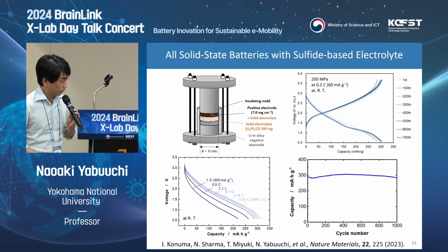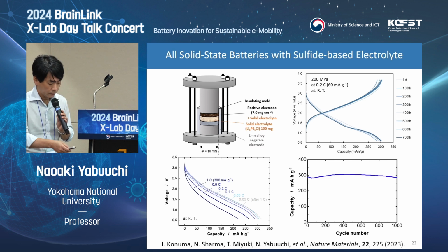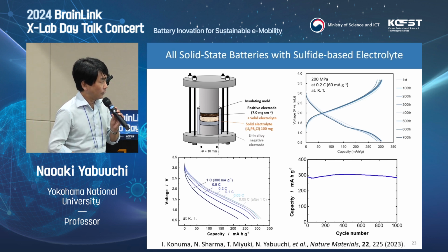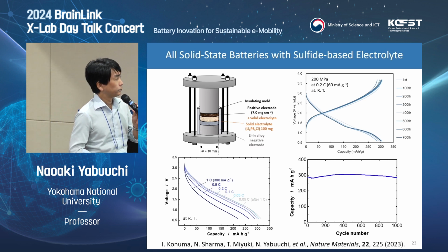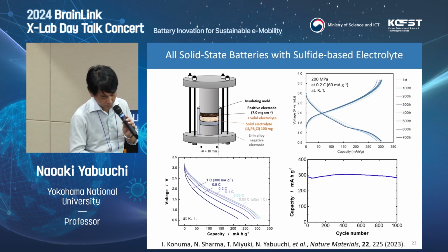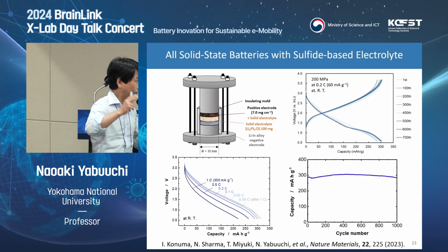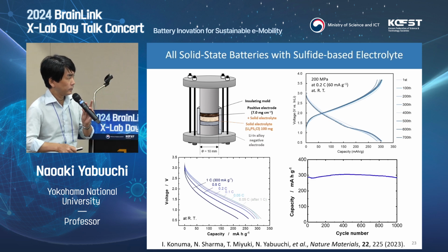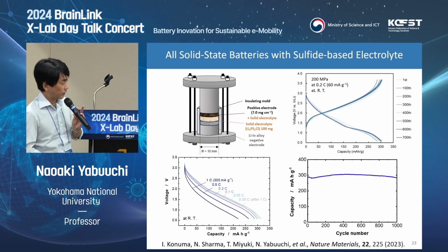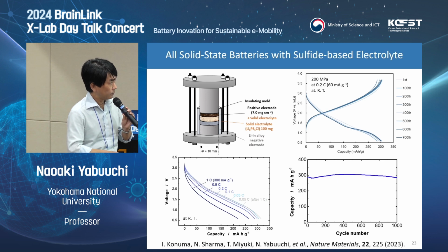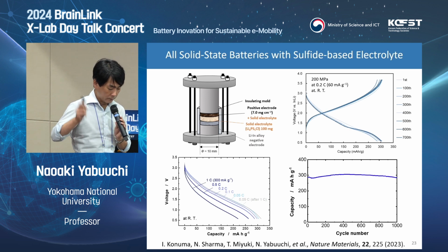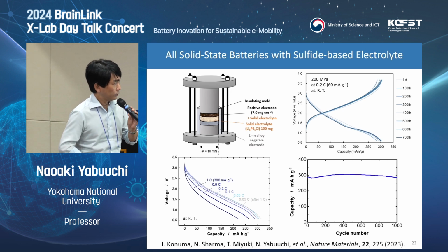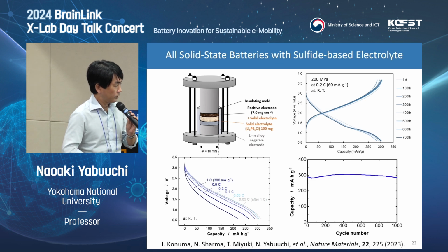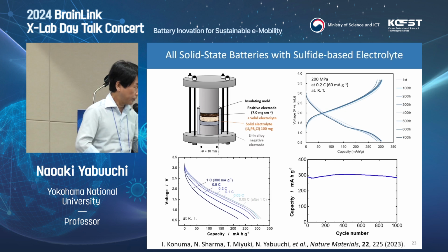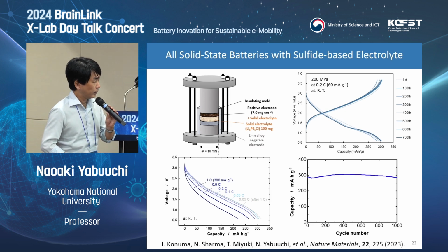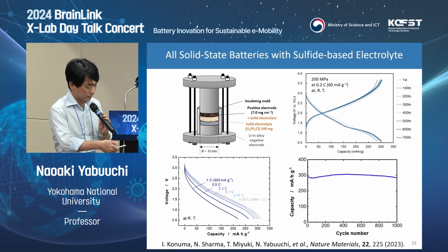This is an important result for our materials' application to solid state batteries. Consider a solid state battery with argyrodite type sulfide electrolytes. Typically, many people use a very high stack pressure like this, 200 megapascal, because with conventional materials we cannot avoid volume expansion and shrinkage. By applying a very high stack pressure, they can make more reversible operation. However, even applying a very high stack pressure, in general with conventional materials, cyclability is not good. However, with our zero volume change materials, now you can see a very highly reversible process. And we were surprised by these results: 1,000 cycles, no capacity fading. So now we can design very long life solid state batteries with zero volume change materials.